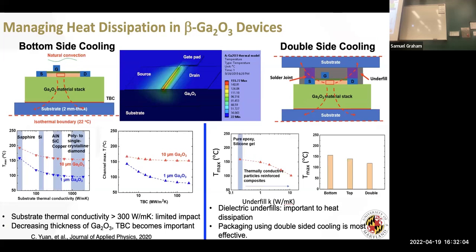I will have heat that has to now pass through this gallium oxide material, and it's going to sit on a substrate. I can have a thermal boundary conductance that's sitting right here. And so what you'll see is that if I have a 10 micron thick layer, or a 1 micron thick layer, as I thin this layer down, the temperature actually drops. Okay, that's expected because I'm reducing the thermal resistance here.